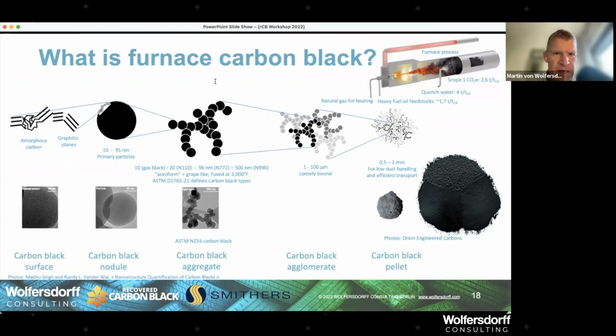First question from Ignacio: is D97 a 10 micron spec for agglomerate size? Now, here's the thing, and this is something I still need to finish in the ASTM D24 working group. The particle names are very different for recovered carbon black and furnace carbon black. Furnace carbon black, we have the primary particles, and then we have the aggregates, which are grape-like, aciniform, and they're fused together, and you cannot even mill these aggregates. And then you have agglomerates, which are several aggregates together. And then you have the pellets, which are a lot of these agglomerates together.